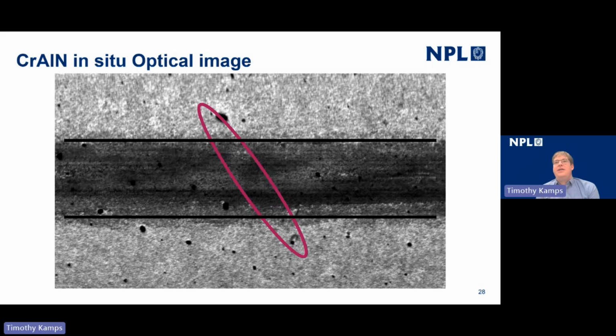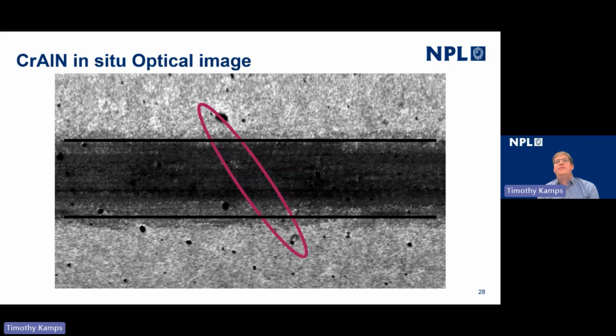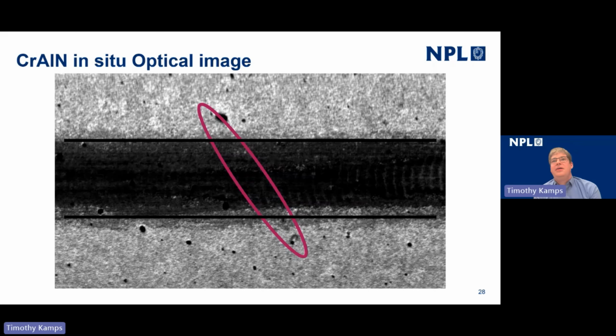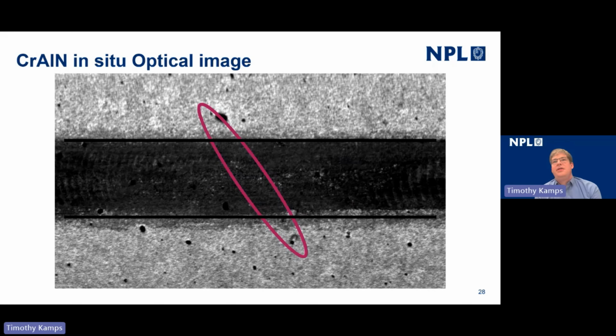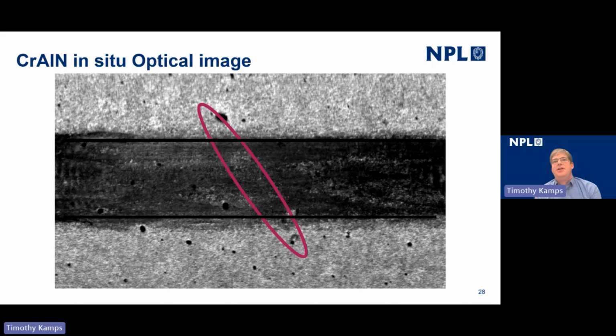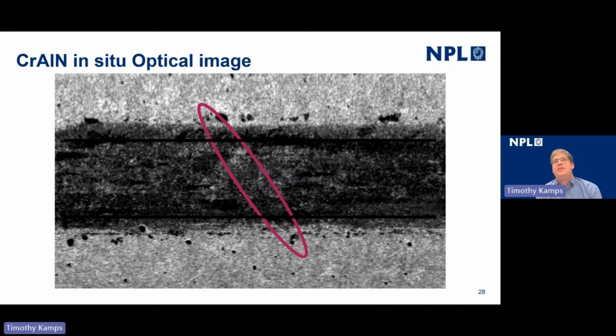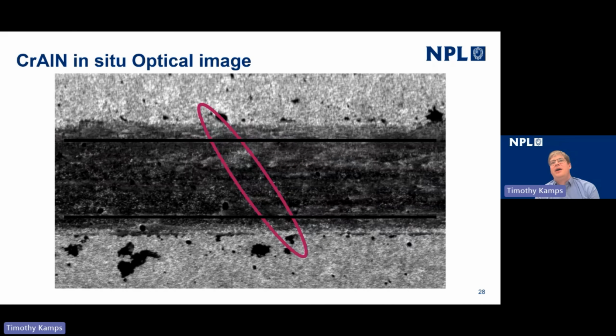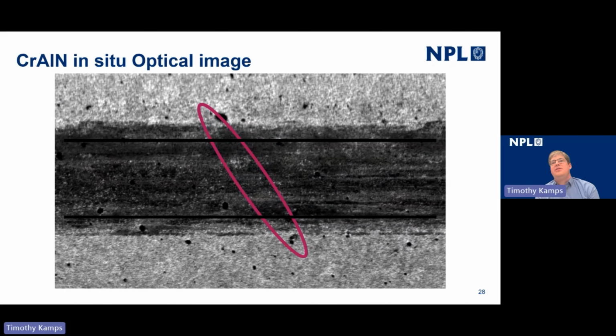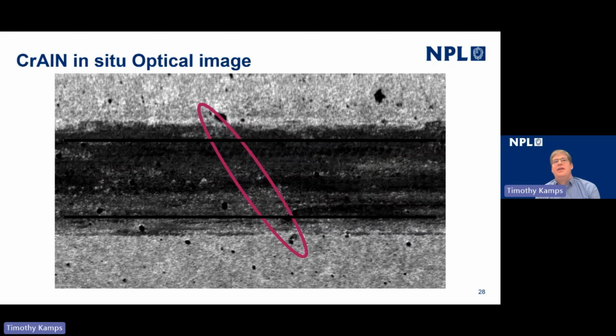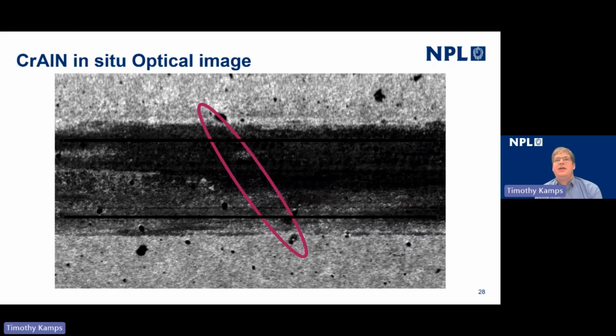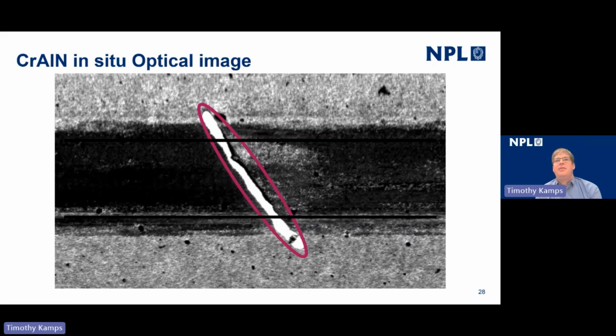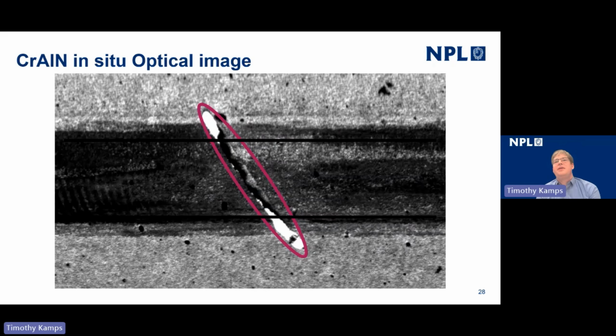This video shows a typical example of the type of information that can be obtained by the system. This is a chromium aluminium nitride coating on an ASP23 disk, having had a silicon nitride ball slid against it. And each of the images that you're seeing is after each successive pass of the ball on the disk. And just then the coating failed. That was the bright diagonal line that formed on the surface.